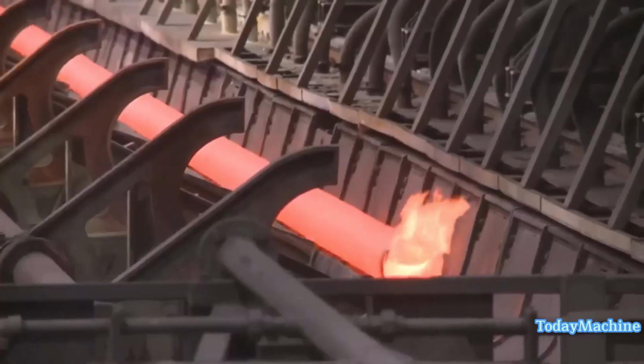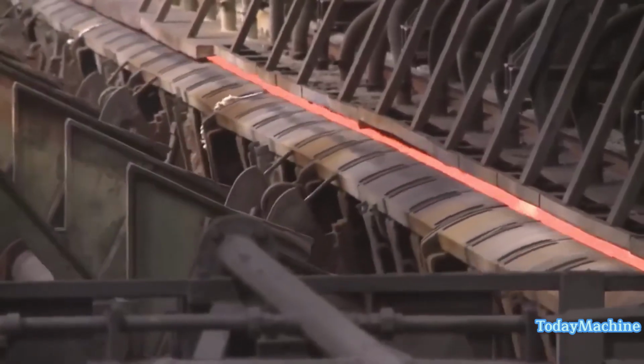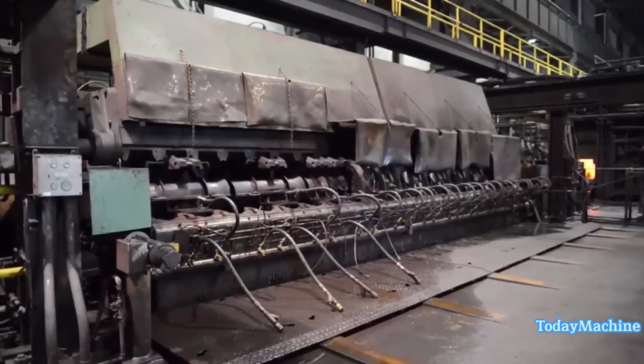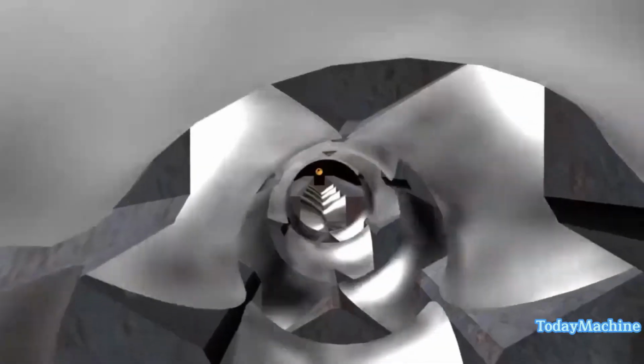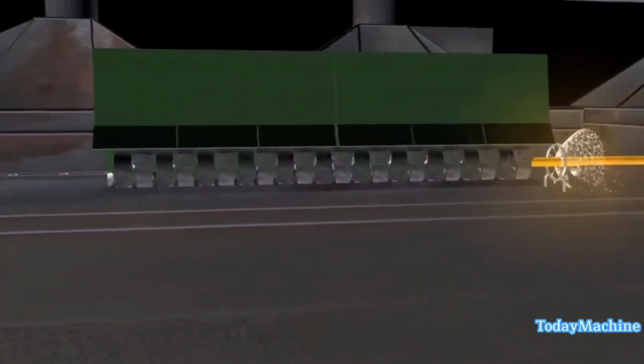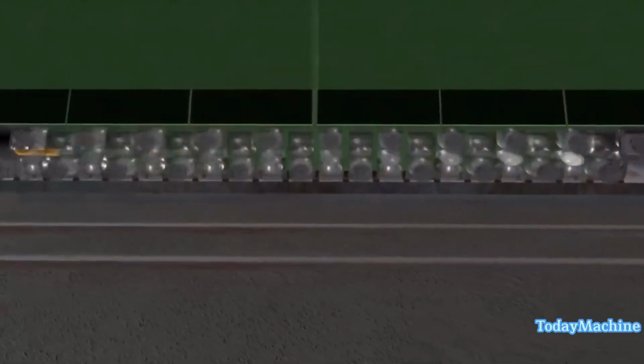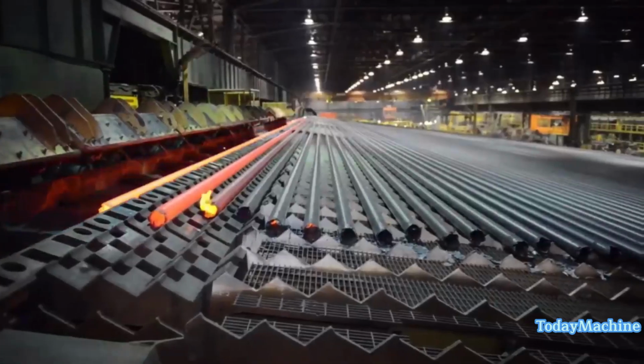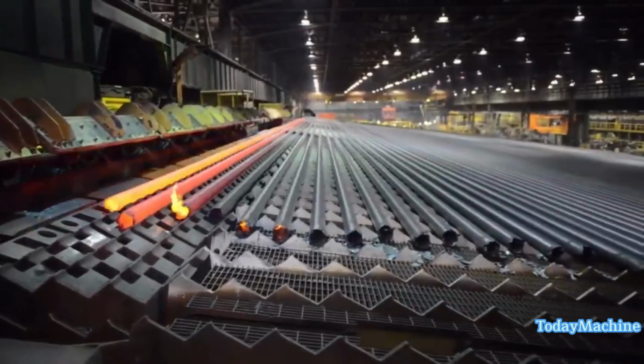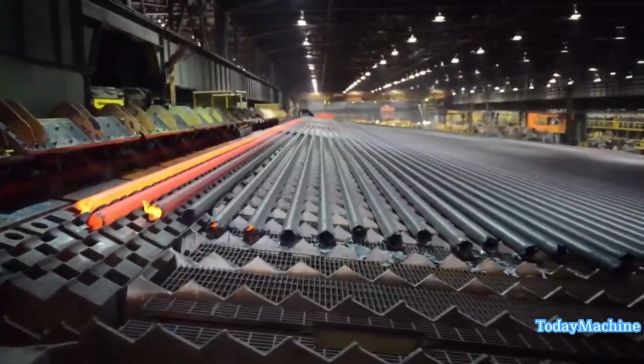The pipe then enters a wall thickness gauge, where it is scanned by 24 laser beams and 9 separate radiographic beams. These measurements provide precise outer diameter and wall thickness measurements over the length of the pipe. The tube is then transferred to a walking beam reheat furnace for reheating before it proceeds to the stretch reducing mill. The final outside dimension of the tube is calibrated on a 22 stand mill, where 3 rolls in each stand carefully stretch the tube to create the final outside diameter.